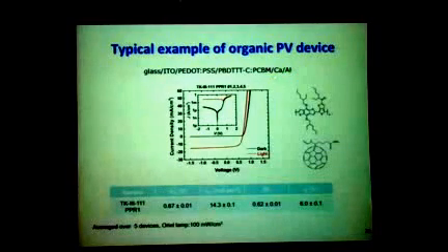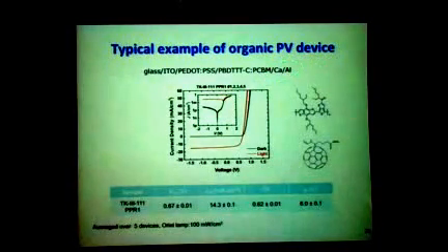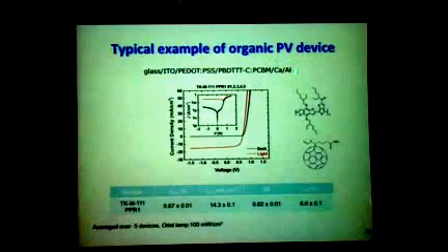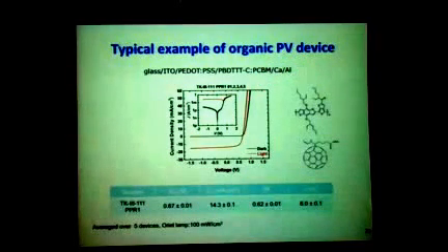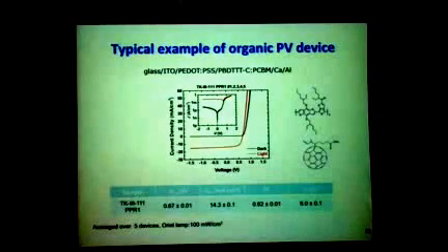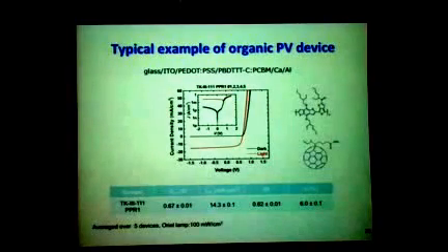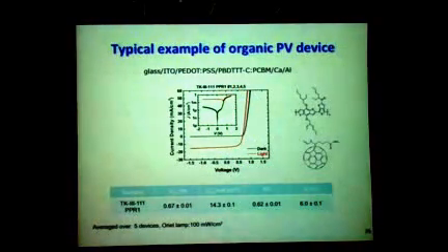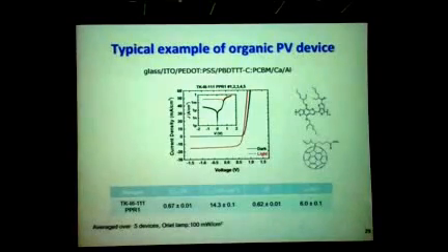The top electron collecting electrode is a low work function electrode, typically involving metals such as calcium, which have the advantage of having a low work function, but unfortunately these materials are highly reactive, so you have to protect these cells extremely well. You can get efficiencies here in the range of about 6% in a cell like this.